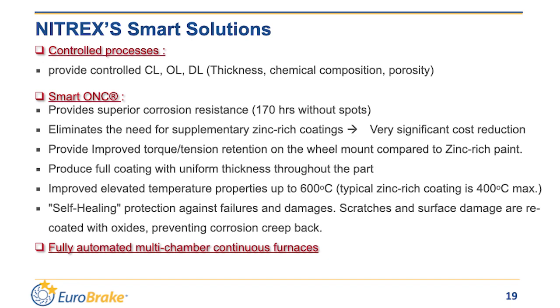So as a summary, the Nitrex smart solutions include controlled processes that provide us with a controlled diffusion layer, oxide layer, and compound layer with different thicknesses, chemical composition, and porosity that can help us to meet almost all the requirements. And the Smart ONC provides superior corrosion resistance up to 170 hours without any spots. Adding to that, there are the self-healing properties that cover and repair the damages that can happen on the surface, and superior protection against any failures.